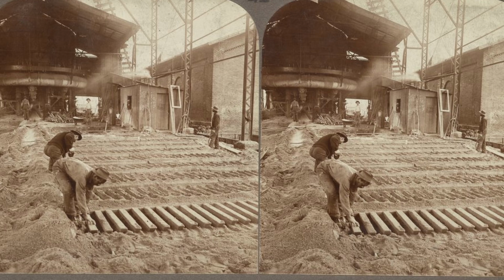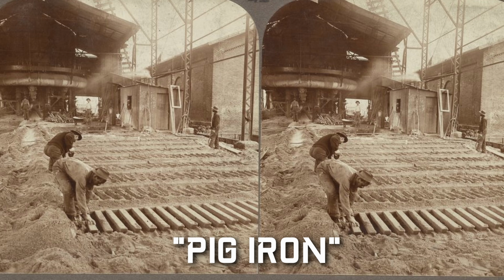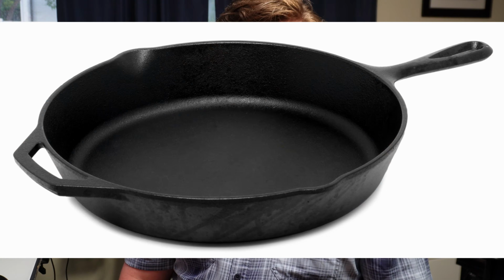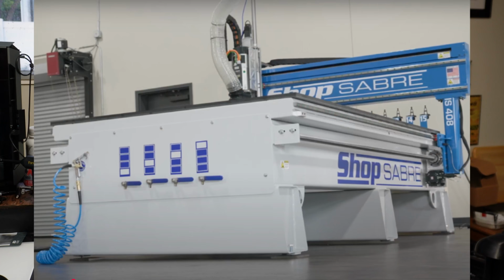This grade of iron can be cast into molds looking like loaves of bread or suckling piglets, hence pig iron. Ever wondered where that comes from? It comes from here. This is not the same as high-strength steel, which is an alloy of iron and carbon. The carbon content of this iron is too high, resulting in a brittle, almost glass-like metallic compound. It is, however, useful for many low-strength applications, and if poured into a different mold, can be made into cast iron cookware, engine blocks, and much more. Cast iron is also very dimensionally stable, naturally damping, and very rigid, so it can be processed into machine bases seen in nearly every modern manufacturing tool today.